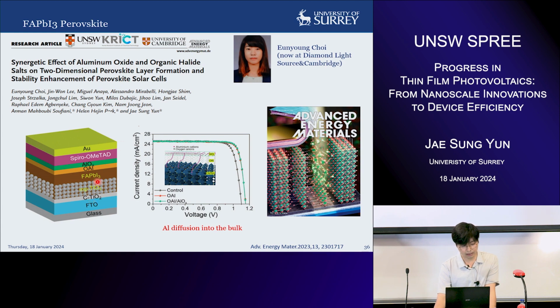So that's the perovskite structure. You have titania underneath the FAPbI3 perovskite, and this long chain iodide is deposited in a very thin way, around 20 nanometers, on the surface to passivate the surface defects. And we employed aluminum oxide deposited by ALD, which is a very convenient way to suppress the evaporation of your halides and ions.